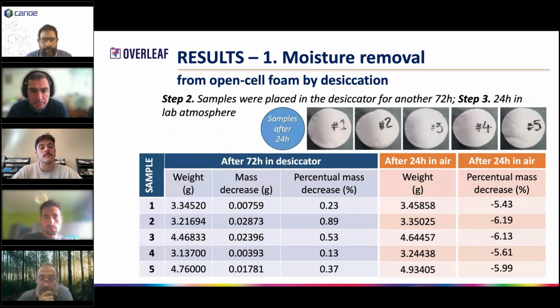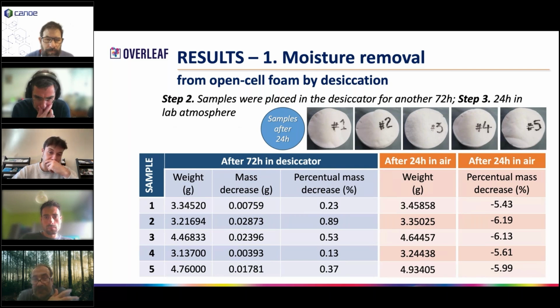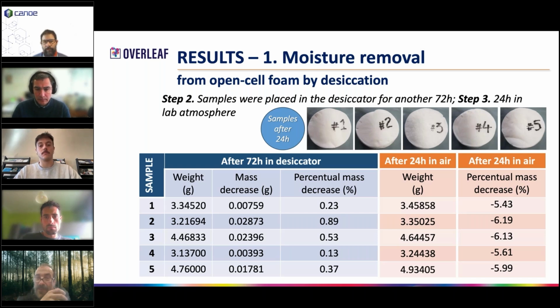Here we have the results after 72 hours in desiccator, and also the weight evolution after 24 hours in air. What do I mean by that? We try to figure out if these samples after water elimination will be capable of extracting back humidity from the lab atmosphere. And indeed, we figure out that after 72 hours in desiccator, the samples that we test were capable of being in a dry situation, but by taking them out from the desiccator, in 24 hours they have the tendency of retaining back humidity from atmosphere.